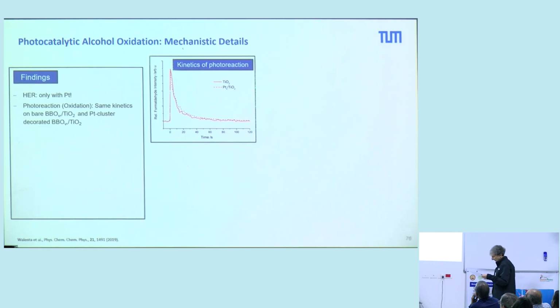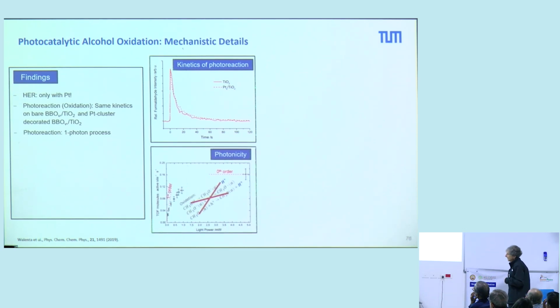Then we can also compare the formaldehyde formation, the kinetics, on a clean surface and on a platinum-covered surface. And you see that the kinetics of this formaldehyde formation is very similar. That means the formaldehyde is really not formed in the neighborhood of platinum. It's on a single site, on these BBO sites. Then we can also increase the photon flux. And you see here at the very beginning kind of linear behavior, first order behavior, and then it saturates. That means we only need one photon.